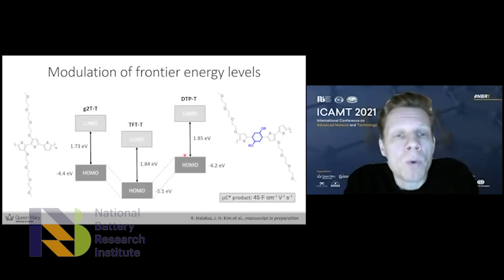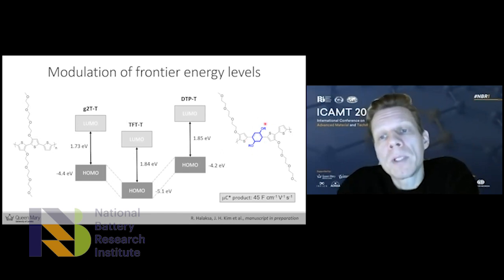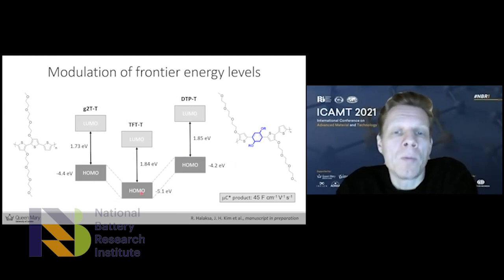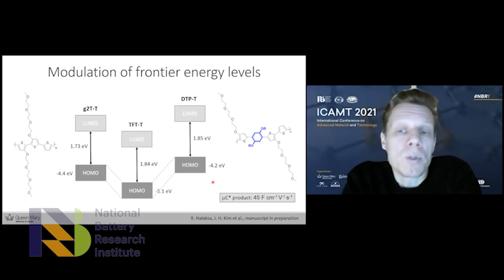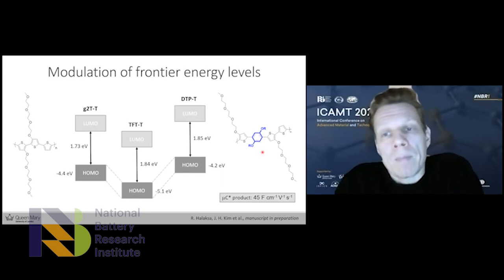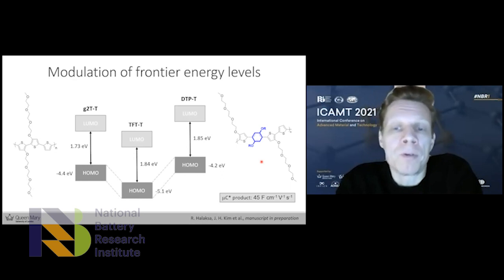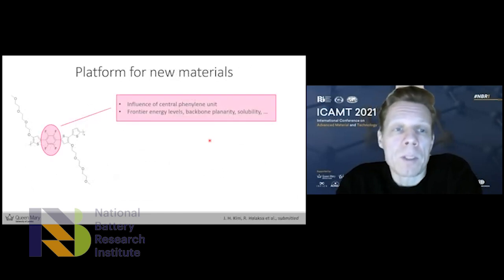So we have started some work looking into this, and instead of the tetrafluorobenzene units, here we have introduced a more electron-rich component, which is a dialkoxybenzene, and we can see that has a significant effect on the HOMO value. We bring it back up again due to these electron-rich components, and also the mu-c star product is increased at least 4 or 5-fold. So we have a whole family of polymers in this class where we are starting to be able to tune the energetics, and we'll be able to tune the performance in terms of the mu-c star product. So that's one promising way of taking these materials.